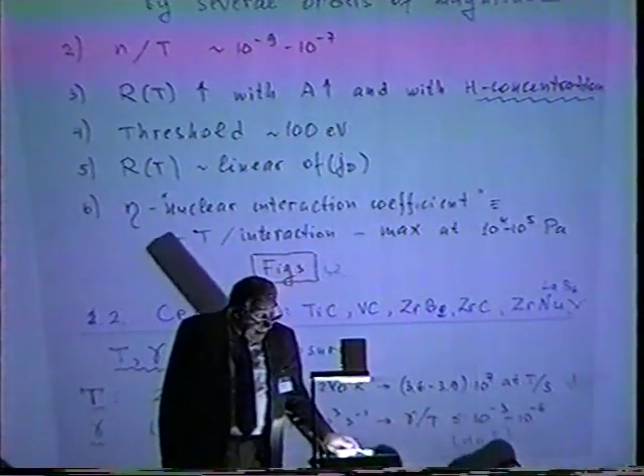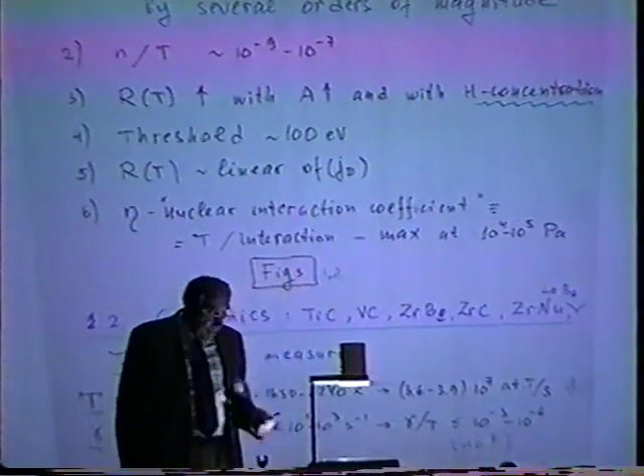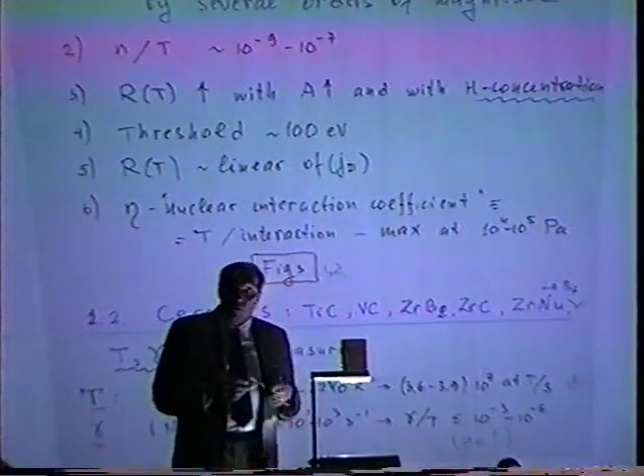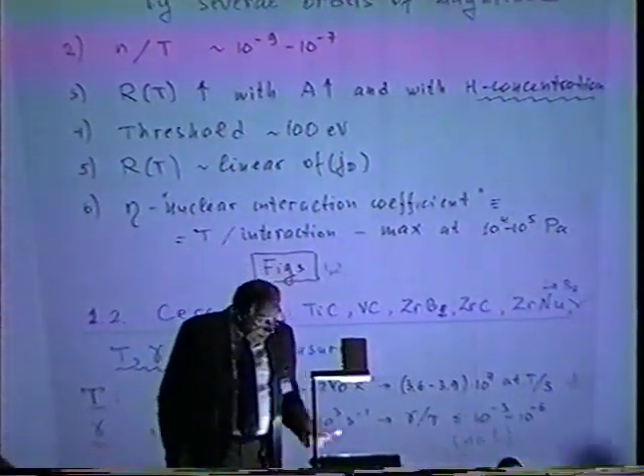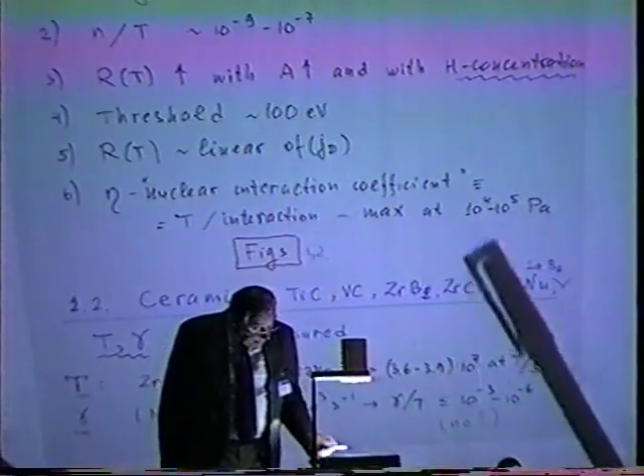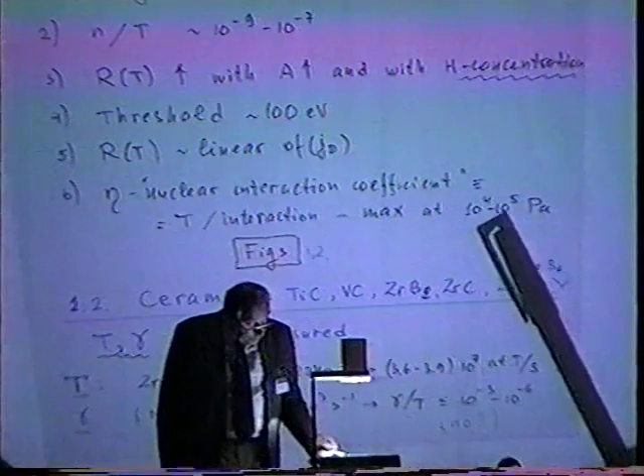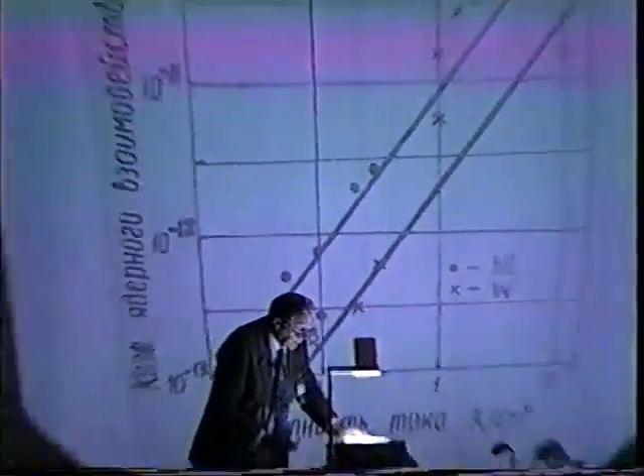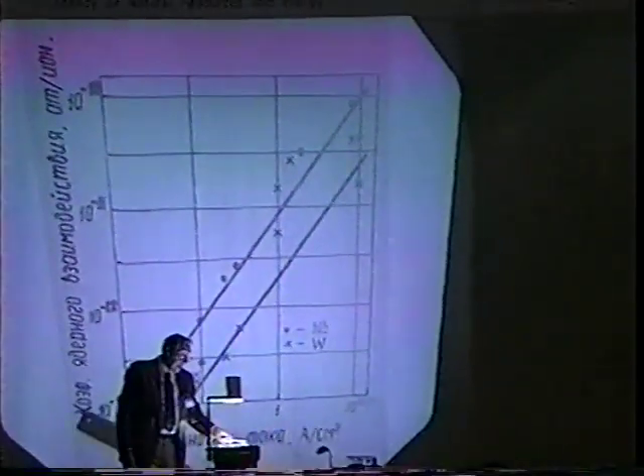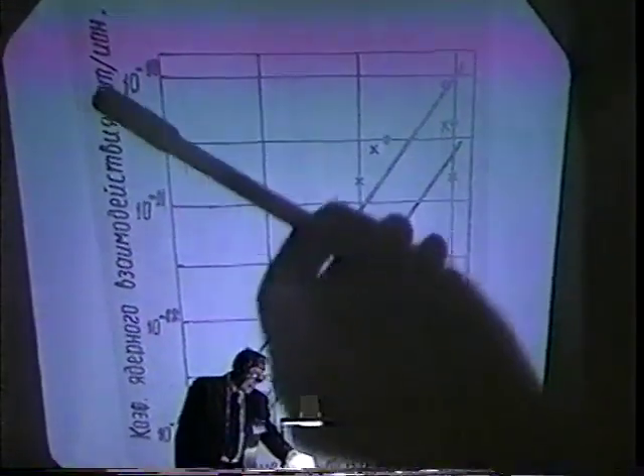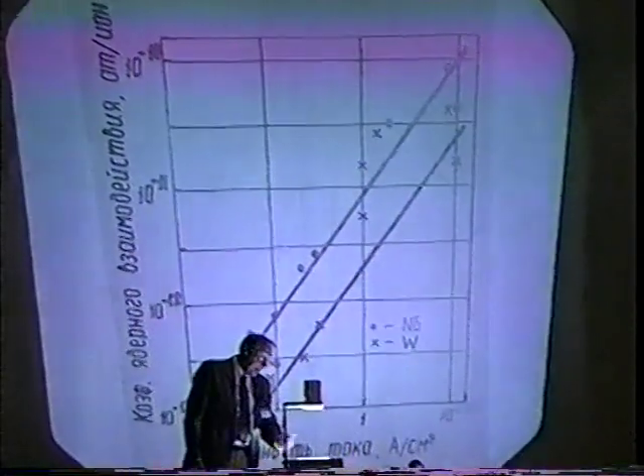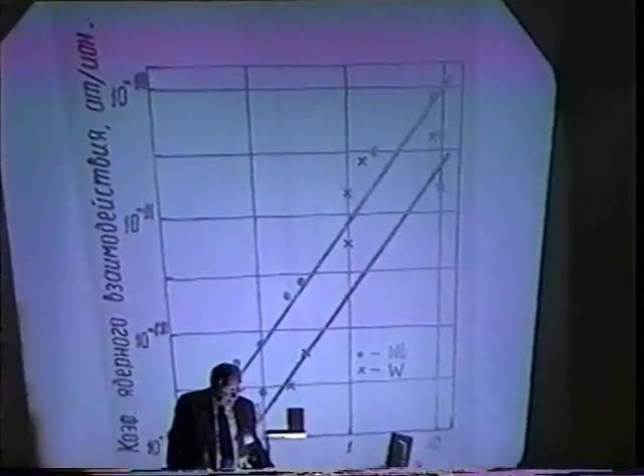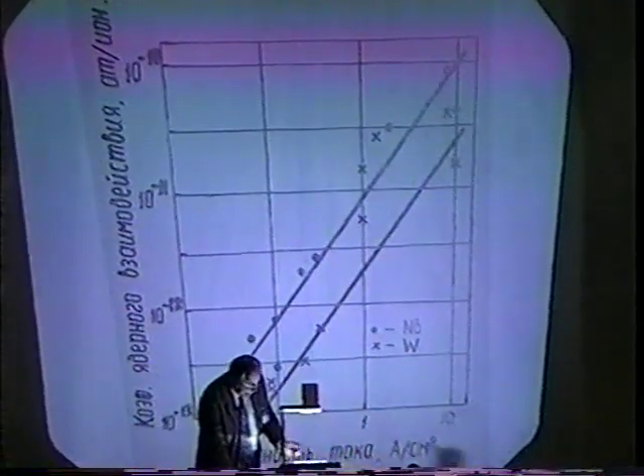And the last point is that the nuclear interaction efficiency, or coefficient, which is a ratio of tritium per one interaction, is maximum at a pressure of about 10 to the 4, 10 to the 5 pascals. And here is a picture which illustrates this result. This is the coefficient of nuclear interaction in atoms per ion as a function of current density. You can see a more or less linear dependence.